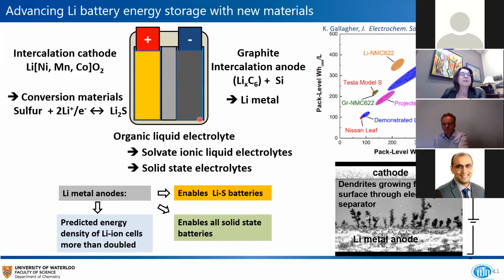And finally, a negative lithium electrode is required for all solid state batteries. It does come with the tremendous disadvantage or problem of dendritic growth. And this shows a real photographic image of such dendrites, which grow from the anode to the cathode. And ultimately, if they pierce the separator, of course, they cause runaway and serious safety issues. So a lot of the problems with all of this new technology is trying to control the lithium metal anode. And dendritic growth is not necessarily solved with a solid electrolyte, as I'll mention later.